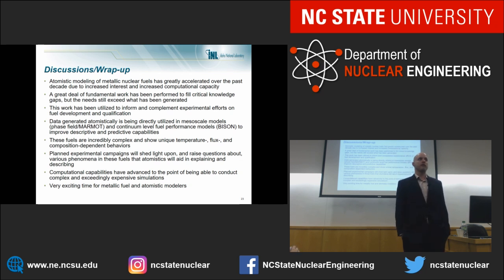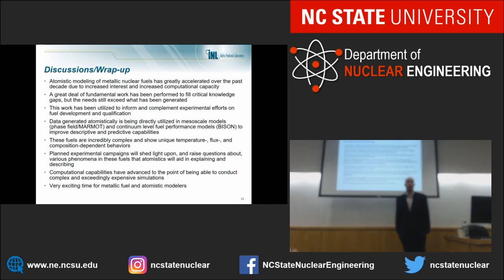But yes, even for just the pure U system, we're getting very different displacement energies, which is a problem. And I assume if we add Zr into these systems, it's going to vary as well, but we don't know how it varies. So that hasn't been studied, hasn't been investigated at all. I've done a little bit of binary collision Monte Carlo work on pure U versus U-Zr. That's only going to tell you some information that's approximated from much higher level models.